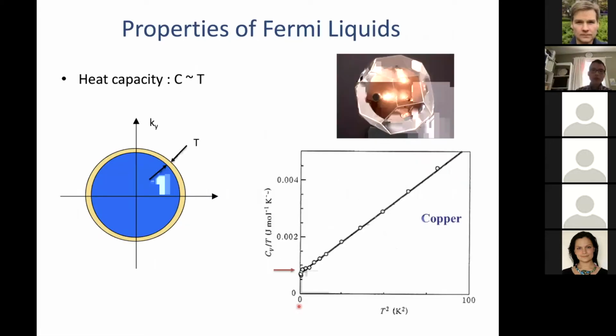Okay. And there are some important physical consequences. So one is the heat capacity. The question is, as you increase the temperature, how much energy you have to provide to the system. And at low temperature, unlike in a relativistic system, you can create the low energy excitation anywhere on the Fermi surface, on this extended manifold of the Fermi surface with, say, thickness T, because energy increases only in the radial direction, right? So therefore, the entropy and the heat capacity increase as T linear, okay? Instead of T to the D in a relativistic system.